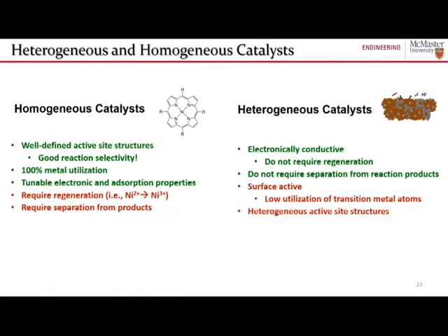And what that means is that every active site structure doesn't necessarily look the same. You can see in that little cartoon I put there, some of those brown atoms or some of those silver atoms are coordinated in different environments. Some are defective, some are in more ordered structures. There's just a lot of variation in how they're configured in this catalyst, and therefore there's big variations in their activities and in their selectivities.